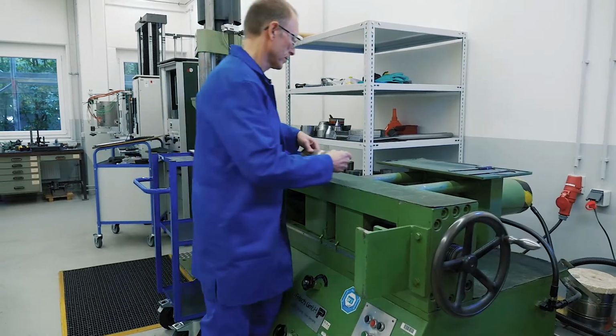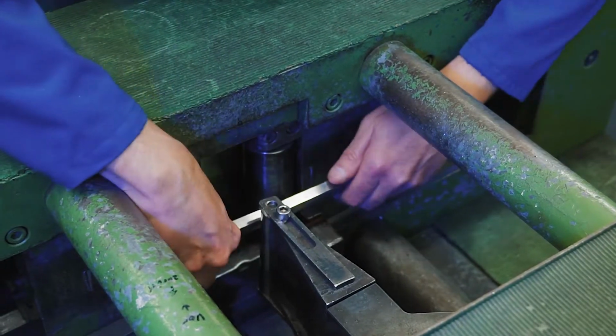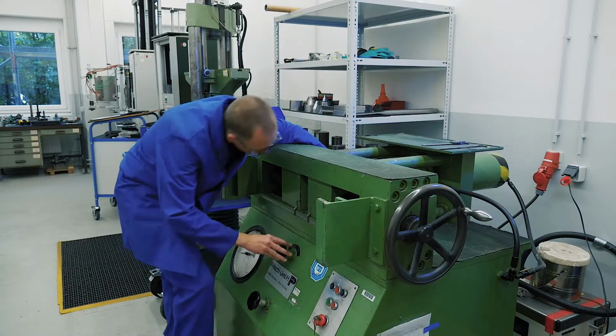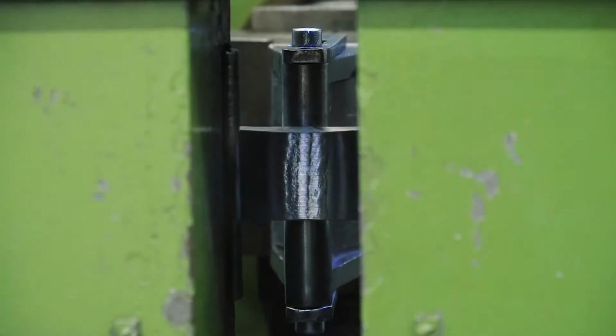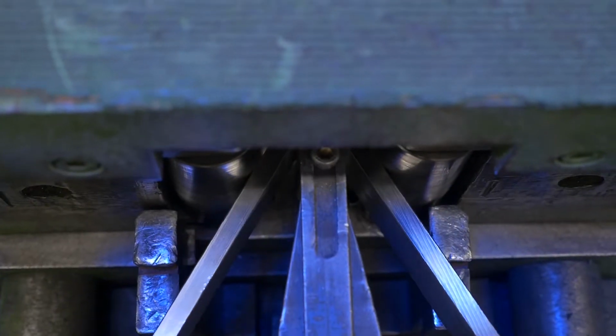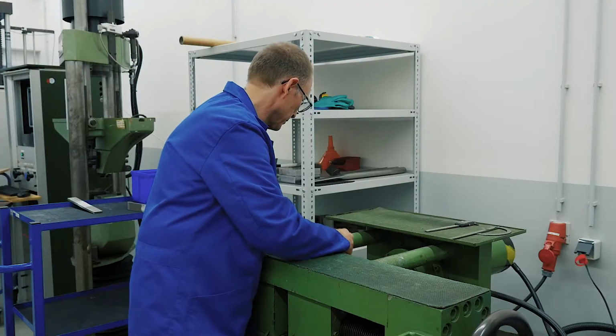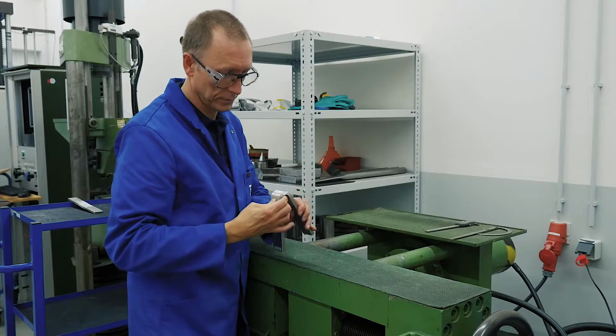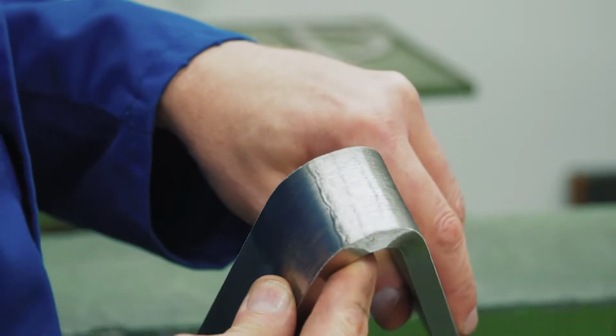In the bend test, we check how the welding seam behaves while undergoing extreme deformation. A breaking weld is a strong indicator of insufficient welding quality. The seam would not withstand an extreme load. Our test piece, however, passed this test.